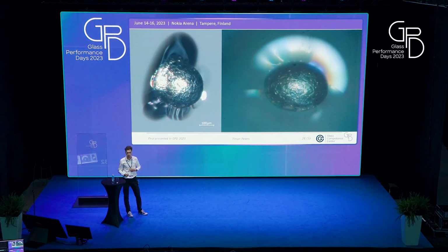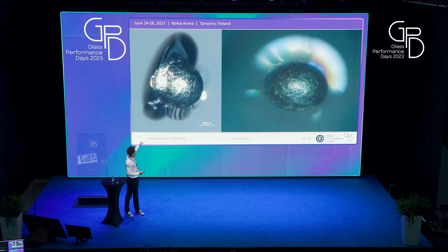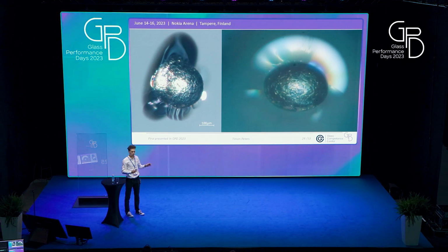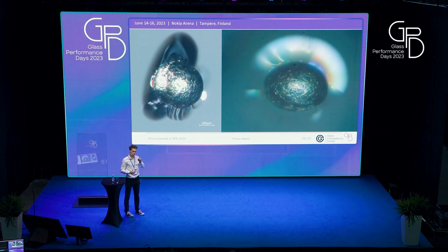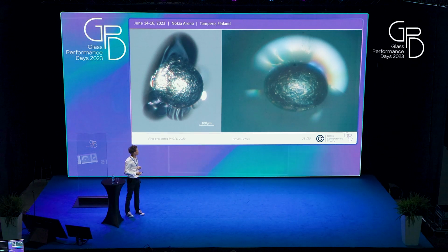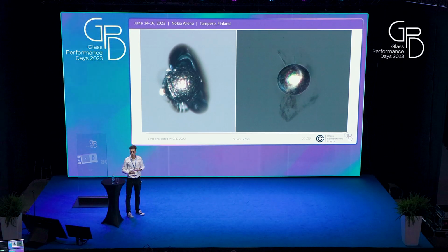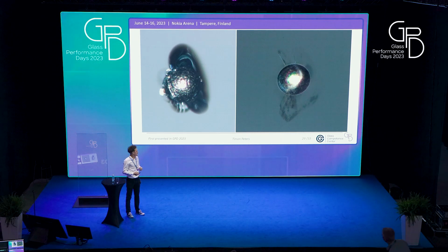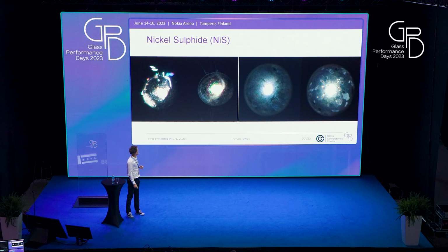You also often find the inclusions with cracks around them, especially if you look from afar. For example, on the one on the left, if you look from afar, you might not immediately recognize that this is a round spherical inclusion, but it may look like some kind of stone if you just have the contour of the inclusion. Also, the cracks that form may sometimes fill with some black matter that we haven't identified yet, but this also makes it difficult.